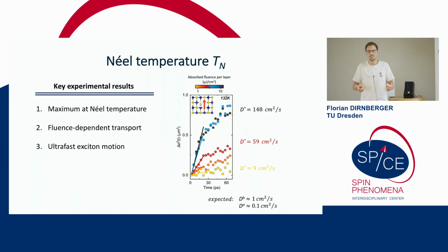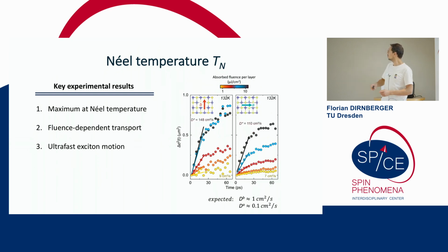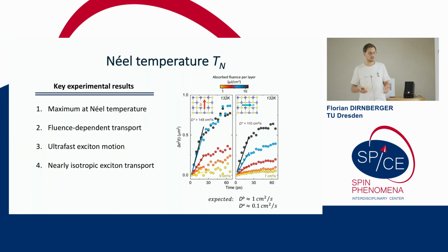Okay, so far I've only discussed this transport along the B direction. Because the effective mass is anisotropic, we know that from band structure calculations, from ARPES, from many other signatures, we really expect that the transport along the B direction should be much faster than along the A direction. However, when we do the actual experiment and we repeat these measurements along the A direction, a surprising result was that the exciton transport seems to be almost the same along the A direction. So there's no huge difference between the A and the B direction, which means that the exciton transport appears to be nearly isotropic in chromium sulfide bromide. It's another result that was not really expected in the beginning.